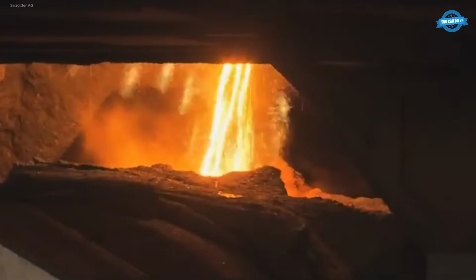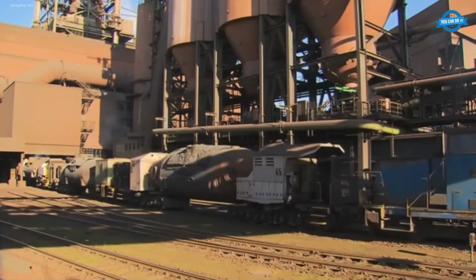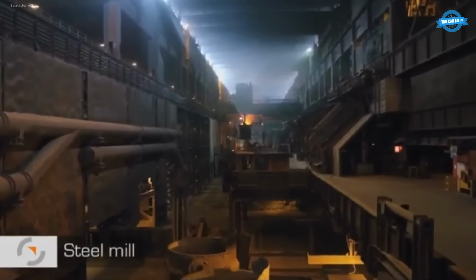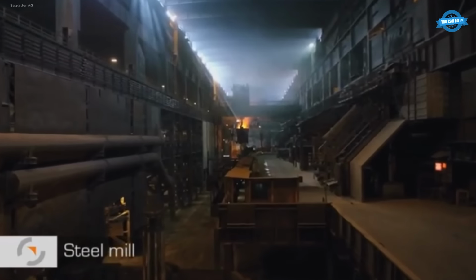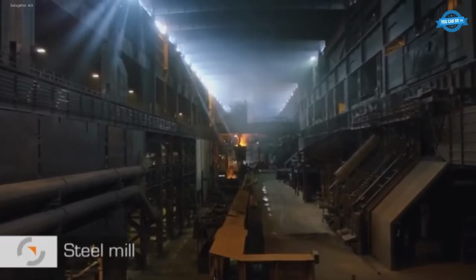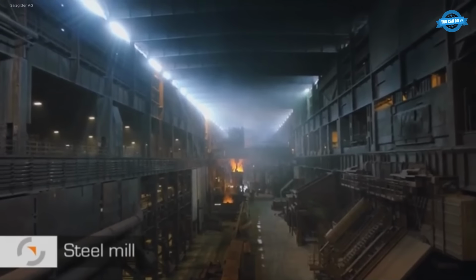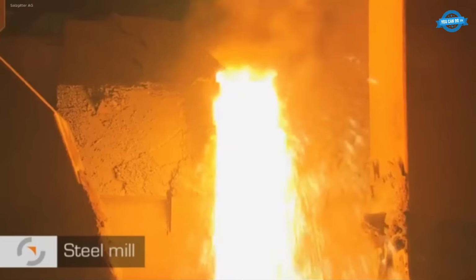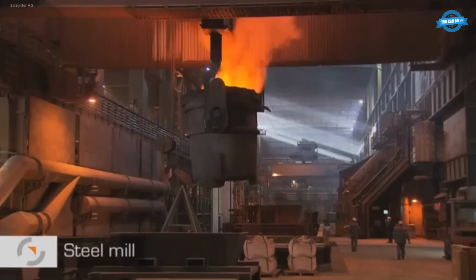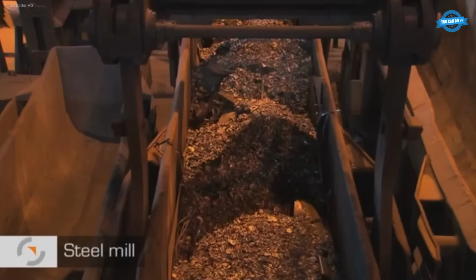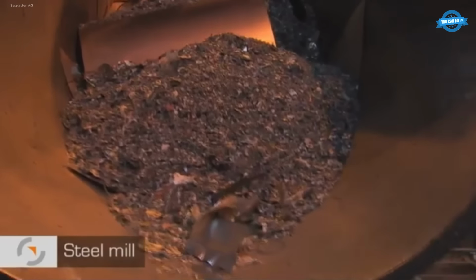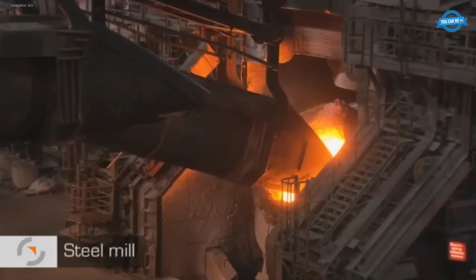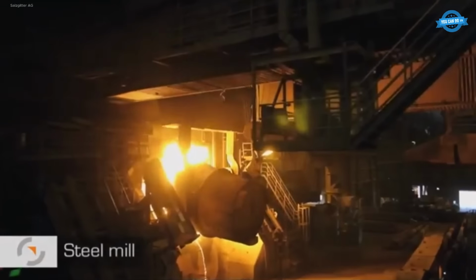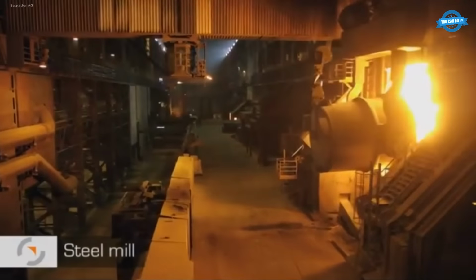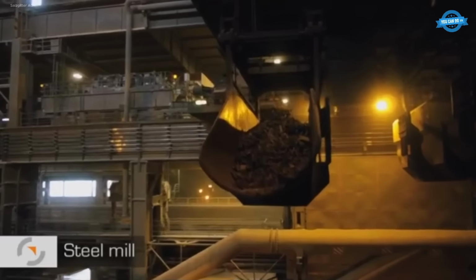At the Salzgitter site, several blast furnaces, the largest over 50 meters tall, produce up to 14,000 tons of pig iron daily. Coke, ore, and lime are layered into the furnace, where preheated air generates processed gas at around 2,000 degrees Celsius. This removes oxygen from the iron oxide, melting the iron in an 8-hour process. Liquid iron and slag collect at the furnace base and are tapped approximately every 2 hours at 1,450 degrees Celsius, where slag separates from the pig iron.